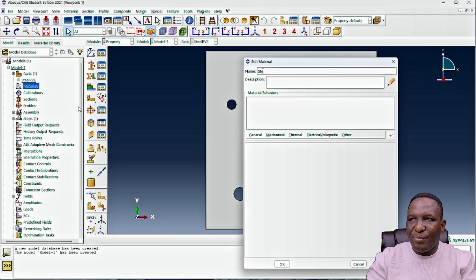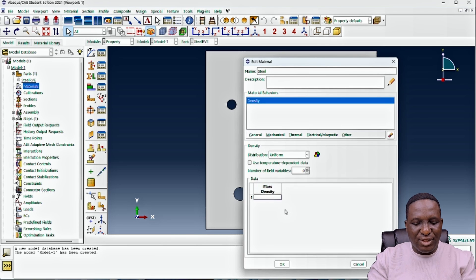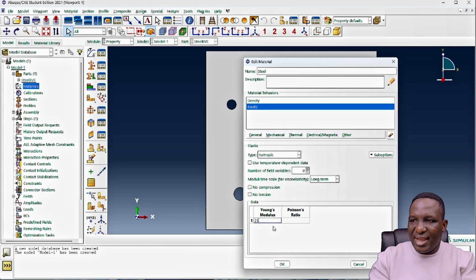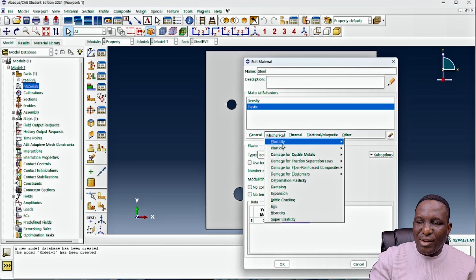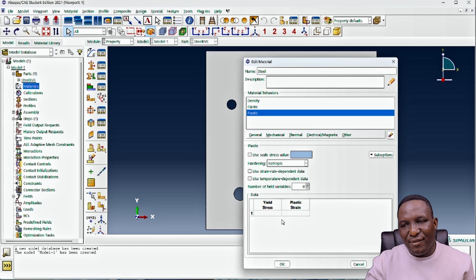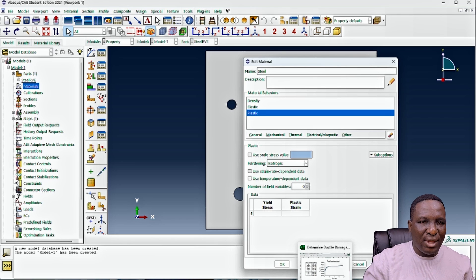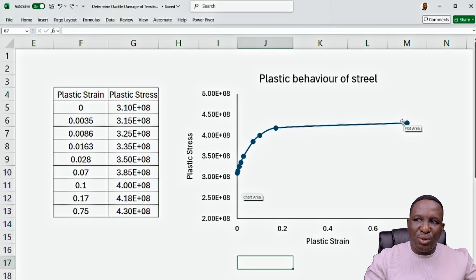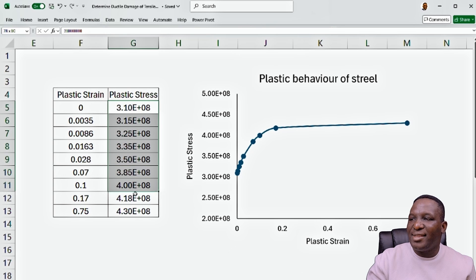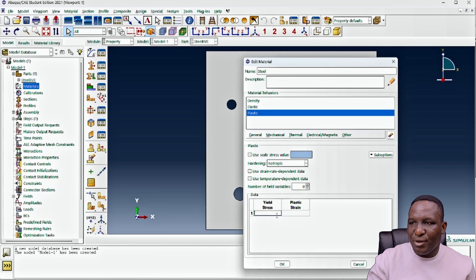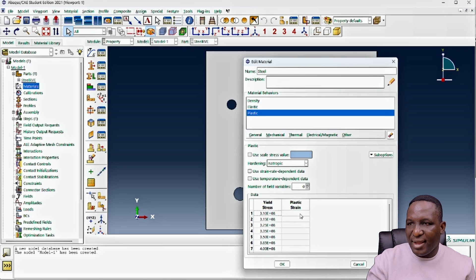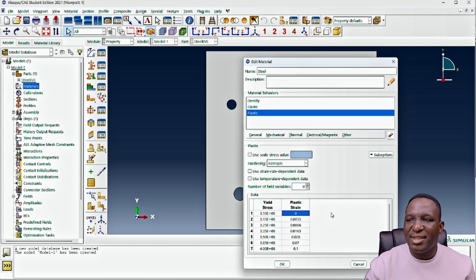The material is steel. We introduce a density of 7860 kg/m³, a Young's modulus of 210 GPa, and a Poisson ratio of 0.33 for the elastic properties. For plasticity, we reference values from a prior ductile damage video. The plastic stress-strain behavior follows a gradual strain hardening format. We paste in the stress values and the plastic strain values to define the plastic stress and plastic strain.